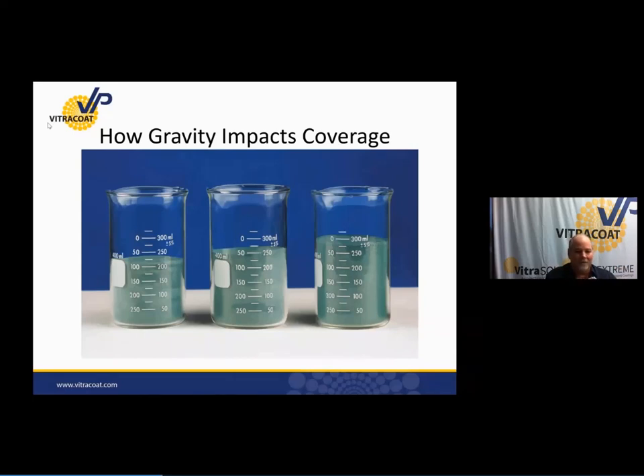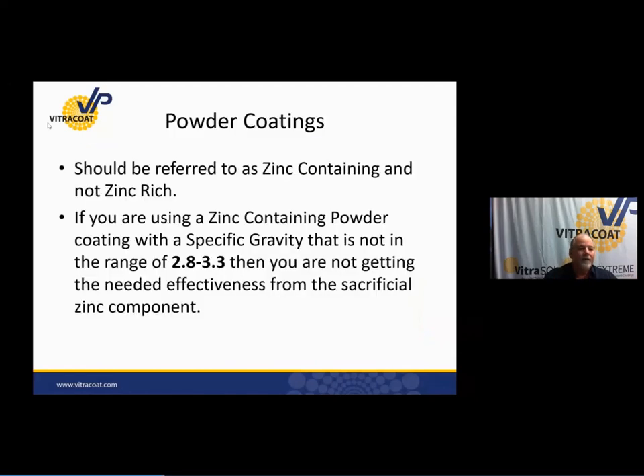And the one on the right is just pure epoxy without zinc at all. So those are the same weights, but different amounts because of the zinc composition. So when you're referring to zinc containing, and I like to say zinc containing powders as opposed to zinc rich, when you're referring to a zinc containing powder, you need to have a specific gravity of 2.8 to really about 3.3 before you really get the added effectiveness of the sacrificial zinc component. So keep that in mind.